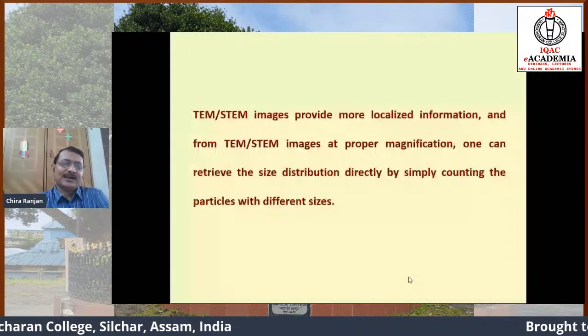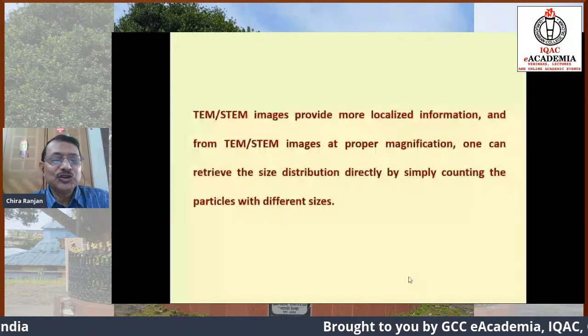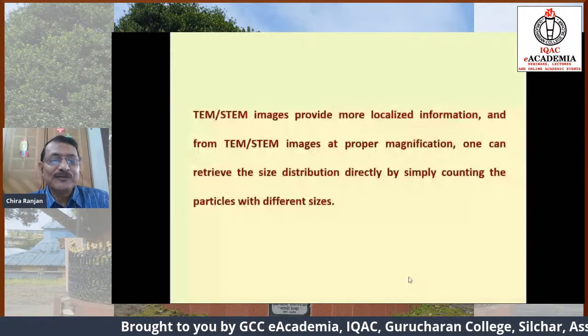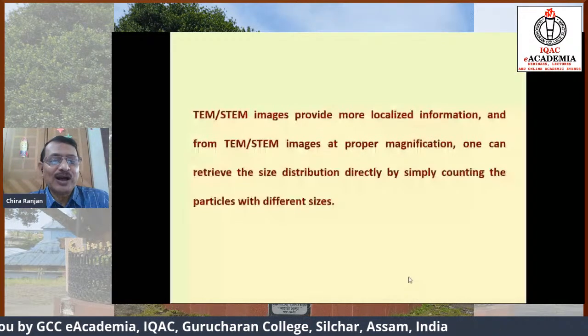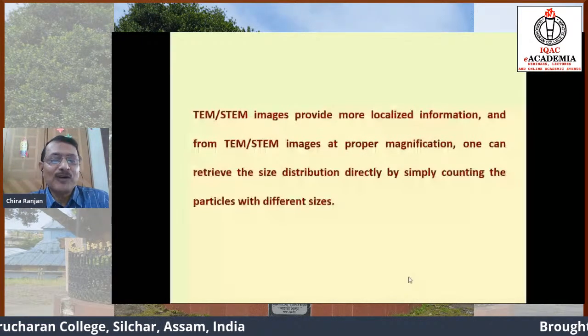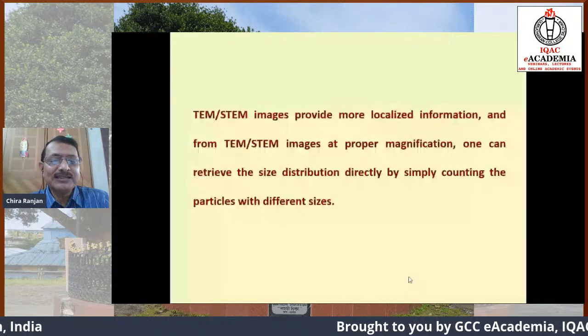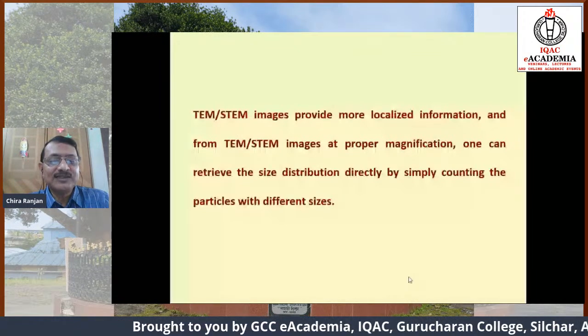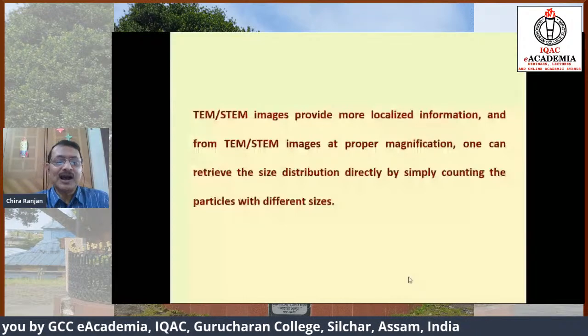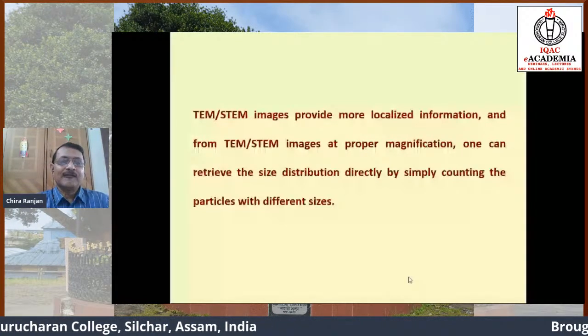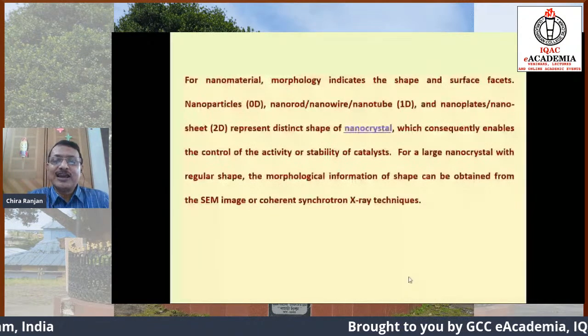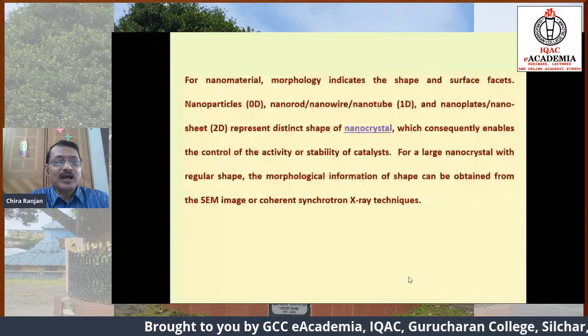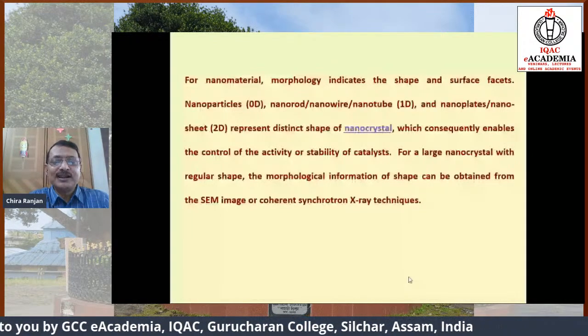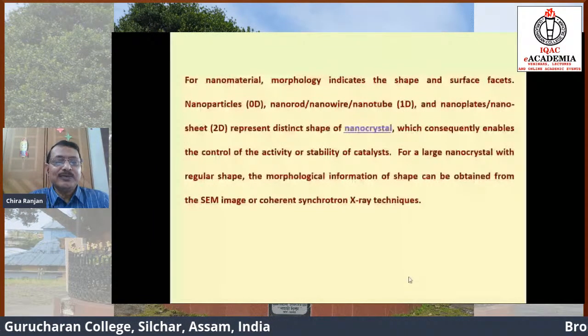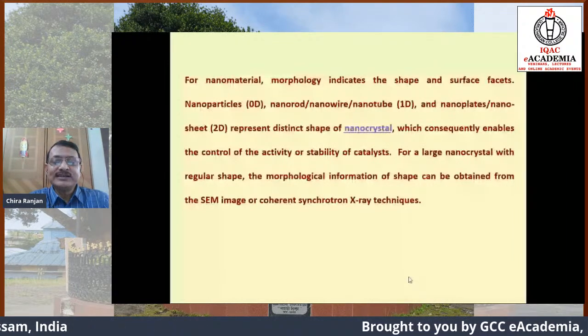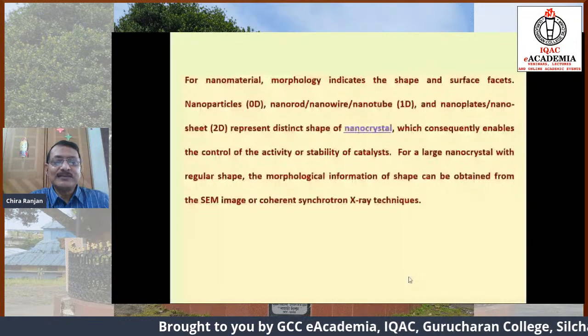So basically, we can continue showing you images, but somewhere I must put a full stop. TEM and STEM images, though I'm not talking about STEM here, provide more localized information. And from TEM and STEM images at proper magnification, one can retrieve the size distribution as well, directly by simply counting the particles of different sizes. For nanomaterials, morphology indicates the shape and surface facets. Nanoparticles, zero-dimensional; nanorod, nanowire, nanotube, one-dimensional; and nanoplates and nanosheets, two-dimensional, represent distinct shapes of nanocrystals, which consequently enables the control of the activity or stability of catalysts.